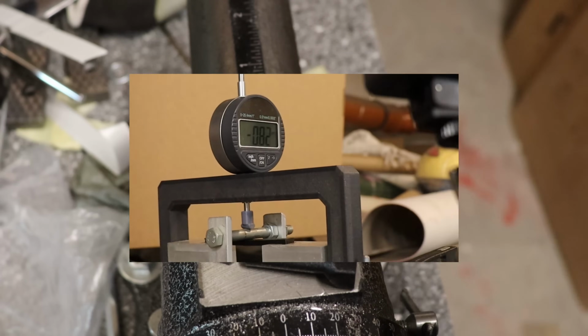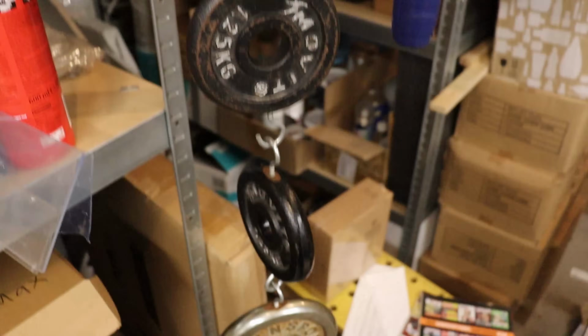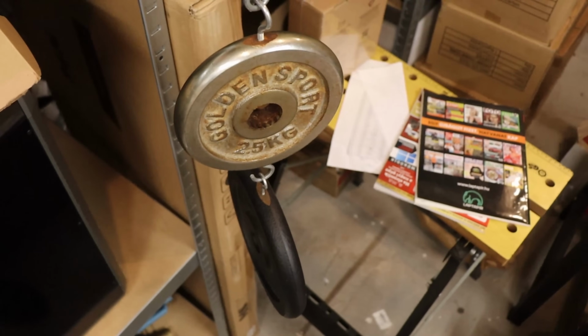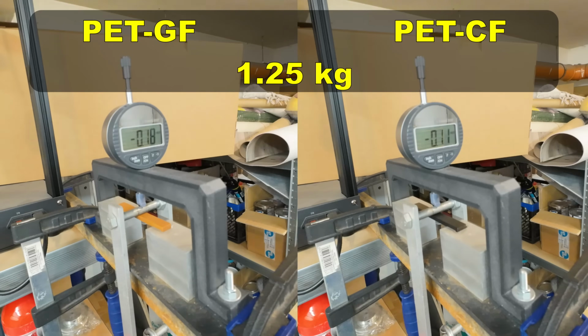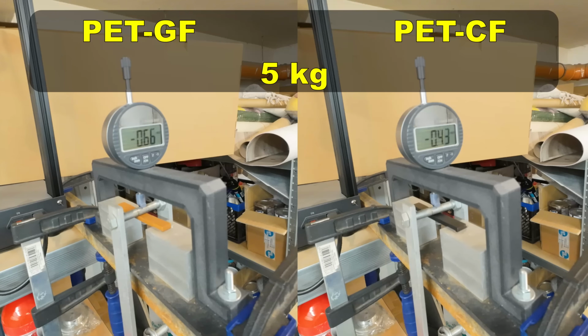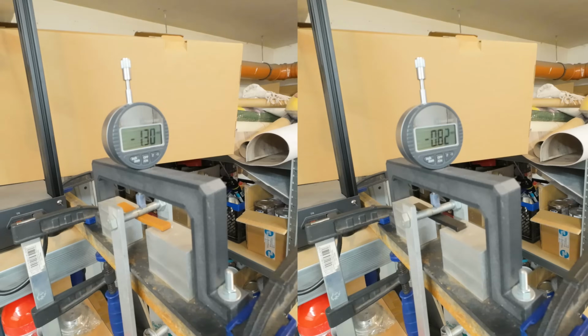3-point bending test, and these loads will be placed one by one, and I'm measuring the deformation after 1, 30 and 60 seconds. Currently this is 1.25 kg load, now 2.5. Deformation under 5 kg. And another 10 kg and quite stiff material with very minimal deformation. Both objects are perfectly straight, so this is not big load for these materials.